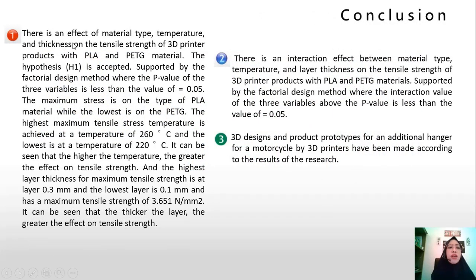Conclusion. There is an effect of material type, temperature, and thickness on the tensile strength of 3D printer products with PLA and PETG material. The hypothesis of each one is accepted, supported by the factorial design method, where the p-value of the 3 variables is less than 0.05. The maximum stress is on the PLA material while the lowest is on the PETG. The highest maximum tensile stress is achieved at a temperature of 260 degrees Celsius and the lowest is at a temperature of 220 degrees Celsius.